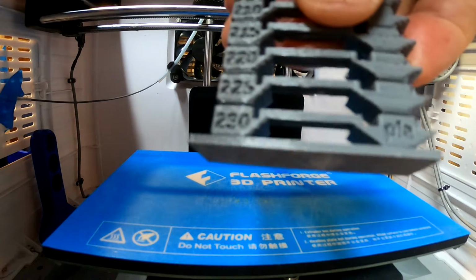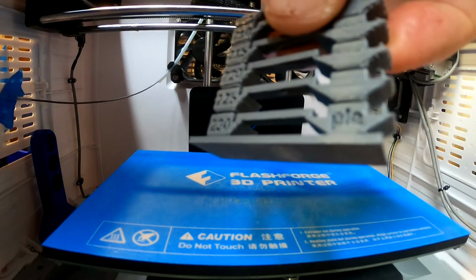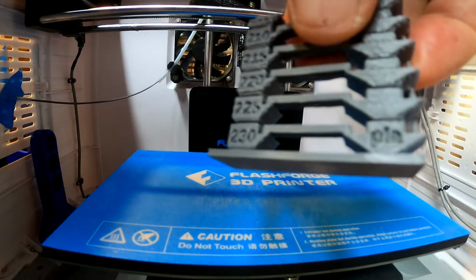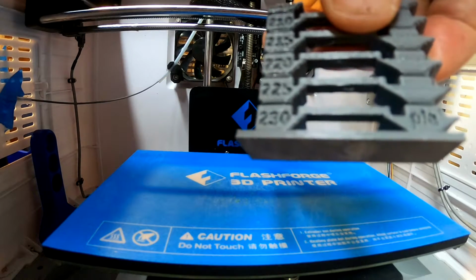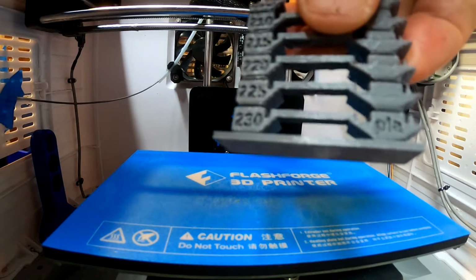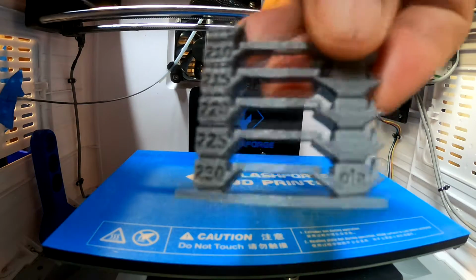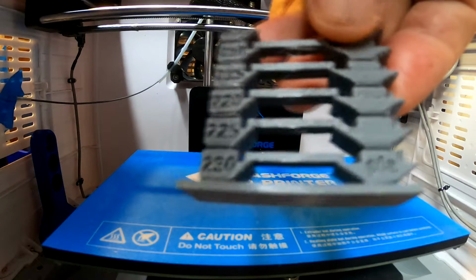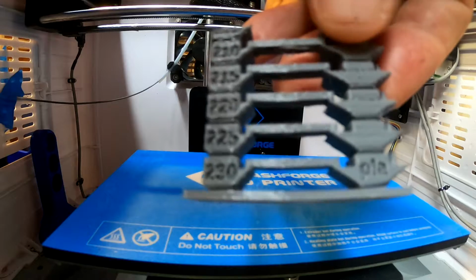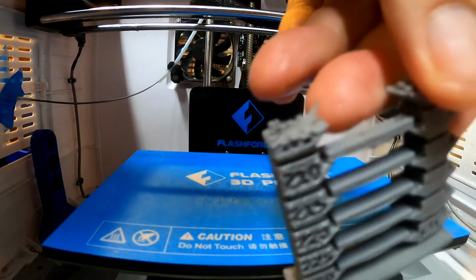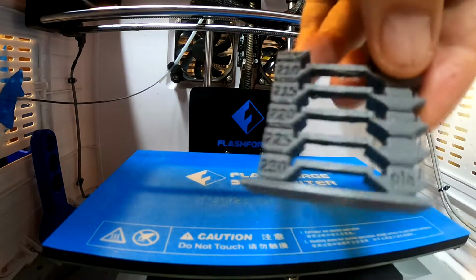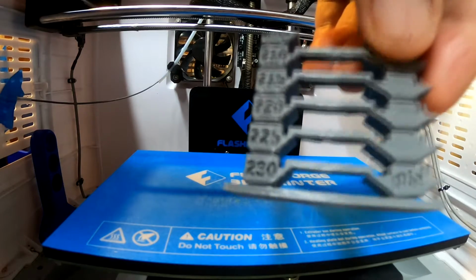230 looks pretty good. The pointy thingy looks fine, and the layer adhesion looks good, but see, as we go up higher, the layer adhesion is starting to fail, and then it doesn't print at all. It clogs up the, I may have to unclog the print head. So 230 looks almost perfect.